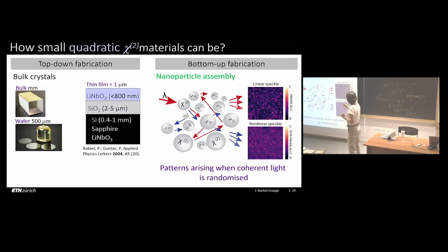And the randomness is really coming from those nanocrystals that have the orientation of their crystal totally randomly oriented. So we are not controlling. When the particles assemble, there is no field applied in that case. So that's why the particles will assemble in a totally random oriented way. And what is most surprising here is that the signal is not at all annihilated, and I will show you why afterwards.